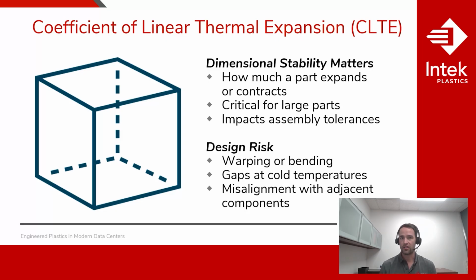Certain fillers, such as glass fibers or mineral, when added to these plastics, can significantly reduce the thermal expansion coefficient and improve dimensional stability. There is a balance, however. If you add too much of these fillers to a plastic, they can become extremely brittle and break when subjected to excessive forces or impacts. So it's really a trade-off between the toughness and durability of your material versus that dimensional stability.